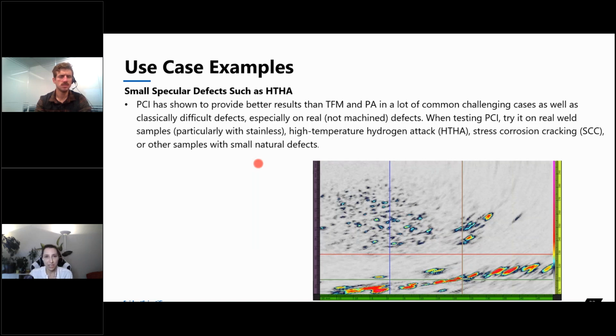Some use cases for PCI, so small specular defects such as HTHA, as we mentioned. HTHA so far has been showing great results with PCI. So we've shown it to provide better results than conventional TFM, which was also heavily used for HTHA inspection, so better than PAUT as well, in a lot of common challenging cases, as well as typical difficult defects, especially as I mentioned, not machined. So a notch will work, but it's not optimized. You really want a true crack with facets. That's how you'll represent it the best.